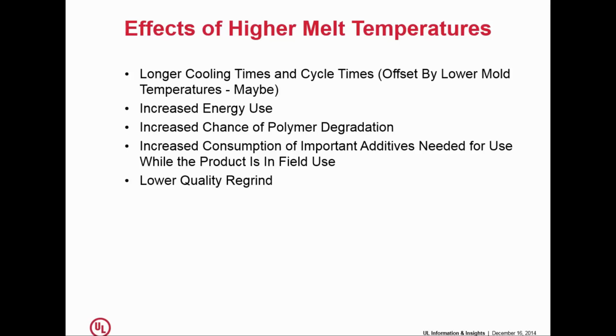You're selling machine time. So if you're not making good use of the machine time, it's costing you money. Also, higher melt temperatures mean higher energy use. Higher melt temperatures mean an increased chance of polymer degradation, which damages the properties of the material. It also means the increased consumption of important additives that are needed for use while the product's in the field. And if you're using your regrind, it also means that your regrind is of a lower quality because it's been subjected to more punishing conditions than it should be. So there's a lot of things that add up here to take away from the integrity of the material as well as the efficiency of your process.